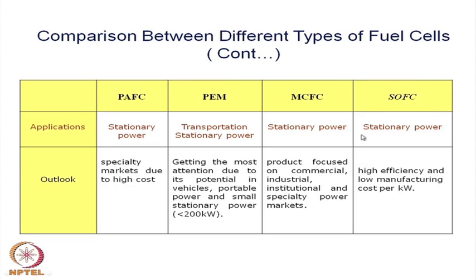SOFC is being considered once again as a stationary power source because of its high conversion efficiency. 50 to 60% conversion efficiency is fairly high, and one can use it for auxiliary power systems. Because it contains ceramic materials, it cannot take a lot of vibrations as well as fluctuations of temperature. So they are brittle materials, and that is one of the major limitations. Otherwise, the driving force for developing such systems is basically the high energy efficiency. These are some of the other remarks.